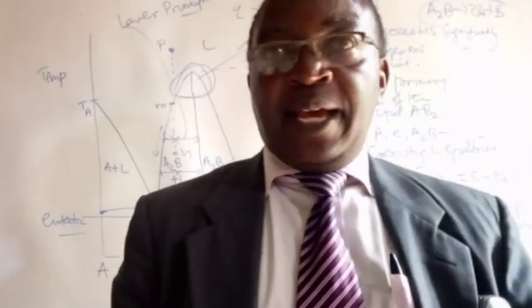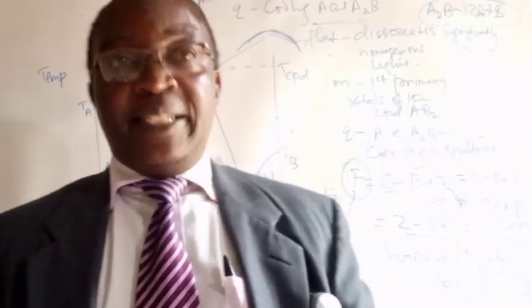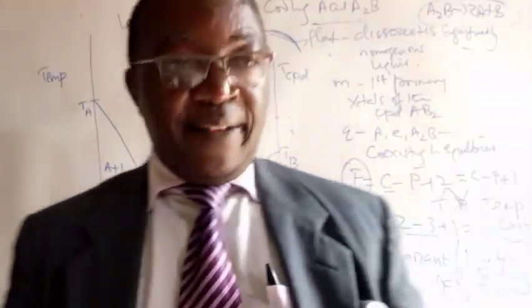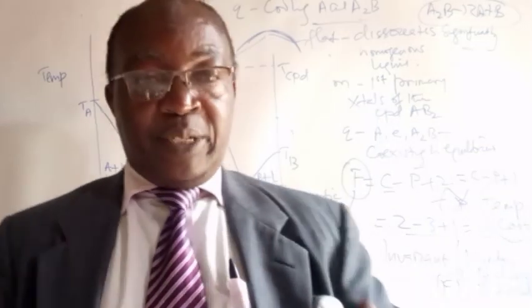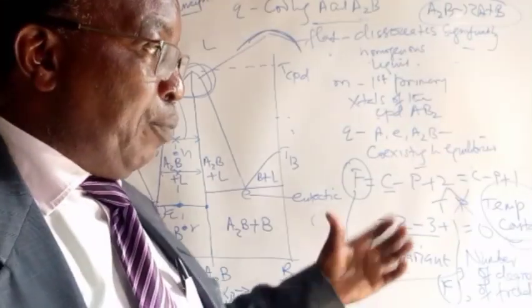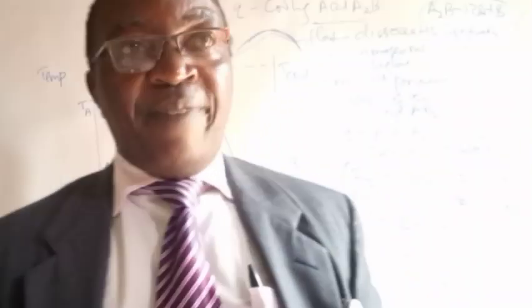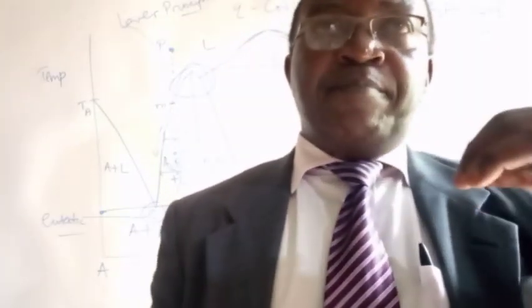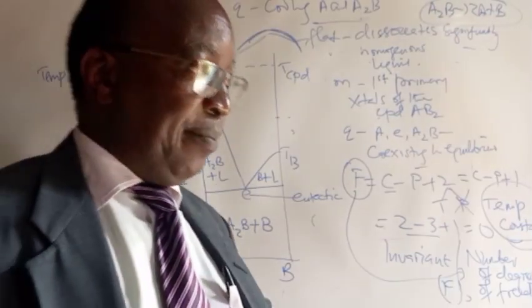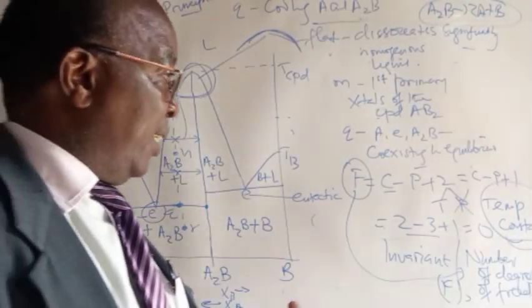Like we gave the example of hydration: if you have a salt which gets hydrated to different degrees, then you'll have several eutectic diagrams associated with those levels of hydration, fused together, juxtaposed together. And number two, in simple cases of simple compounds, you'll find in general that the melting point of the compound is higher than that of the individual elements or components, and that is standard.